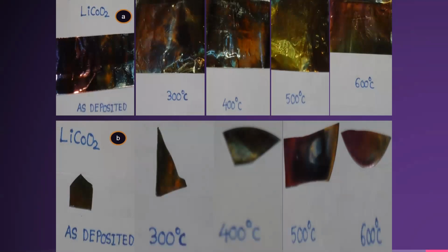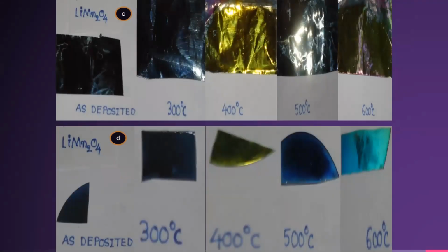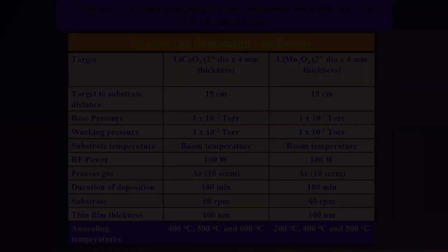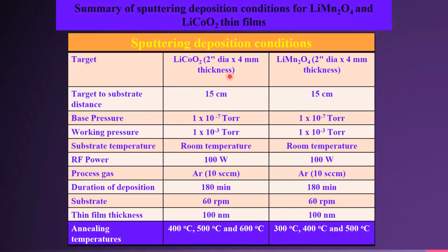Here we can see we have taken lithium cobalt oxide and lithium manganese oxide samples for the lithium targets, and we can see the conditions. For lithium cobalt oxide, the target is 2-inch diameter and 4 mm thickness, and similarly lithium manganese oxide has the same target. Substrate to target distance is 15 centimeters, substrate temperature is room temperature, and RF power is fixed at 100 watts for lithium cobalt oxide and lithium manganese oxide. The processing gas is argon, duration of deposition is 180 minutes, substrate rotation is 60 rpm, and thin film thickness of the target is 100 nanometers.